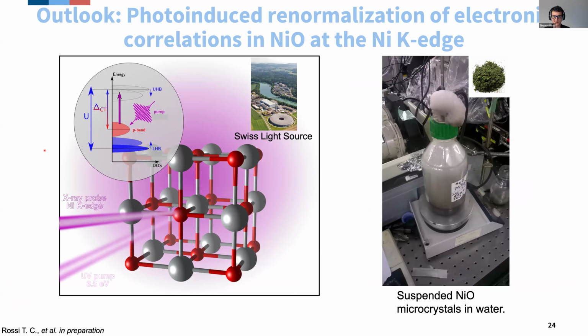So the experiment we did was some time ago already. This was at the Swiss Light Source. We worked on microcrystals of nickel oxide. Those were suspended in water. It was actually quite difficult to suspend them. You can see some foam here that's generated by the tensioactive molecule that we put in the solution to be able to suspend the microcrystals.